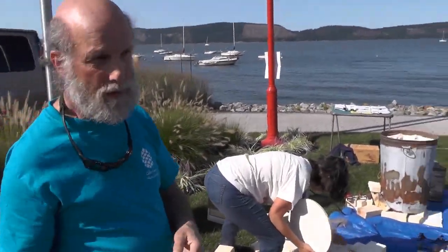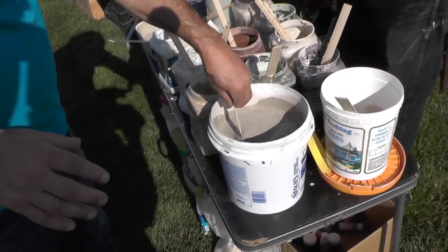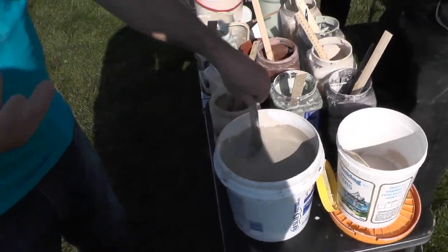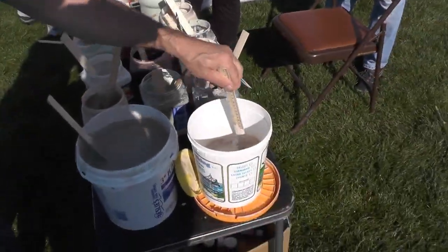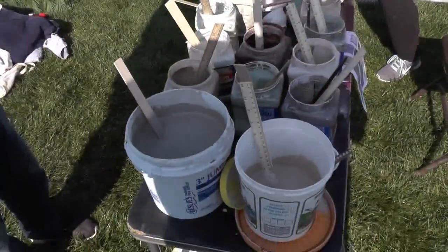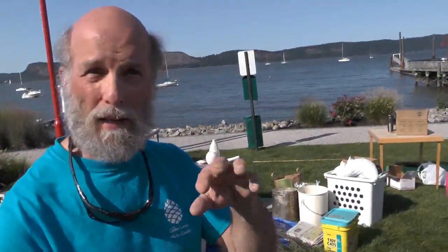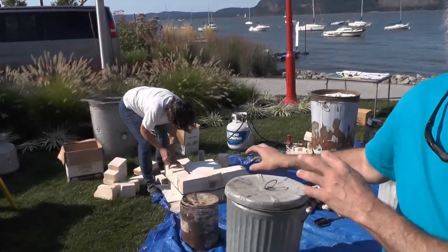There's a third technique we're going to use, where we're going to cover this pot with no glaze with something called slip, and it's just another clay, not the same clay that the pot was made of, mixed with water. We will coat it and we'll put a little bit of glaze on it and fire it. Now this slip on the outside doesn't attach well to the original pot, because the original pot's already been fired and this is still wet. And so as it shrinks and dries, it'll start cracking and leaving gaps between the slip and the pot. When we take it out of the hot kiln and put it in the reduction chamber with the smoke and the fire, the carbon will penetrate the clay under the slip where there are gaps, where the cracks are.